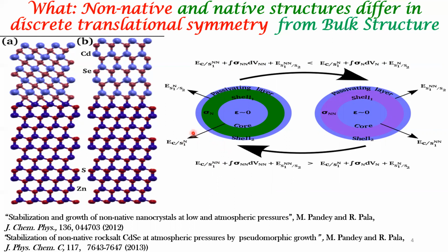We had looked at the interfacial energies involved in the pseudomorphic stabilization of CdS in the rock salt structure, the mechanical stresses involved, and we had provided thermodynamic criteria on when CdS can be stabilized in the rock salt structure as opposed to the bulk wurtzite structure. We had generalized these themes for a variety of systems, and some such systems are provided in these two publications.